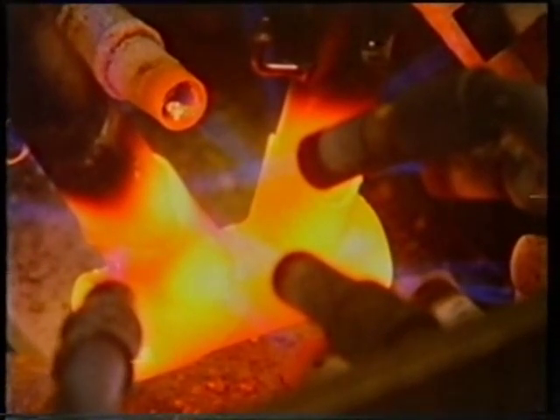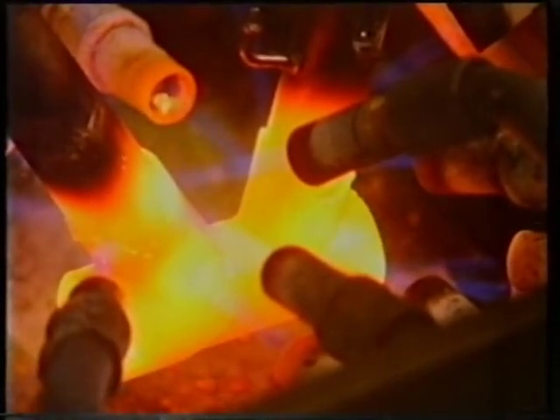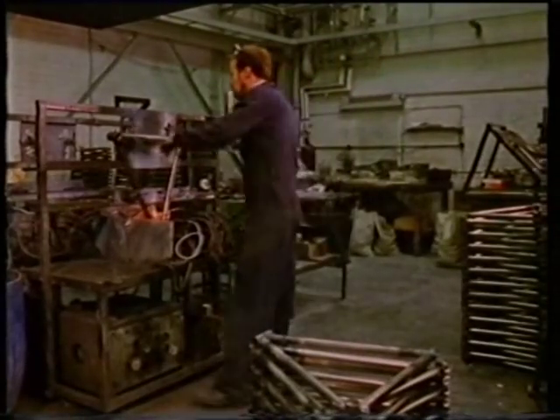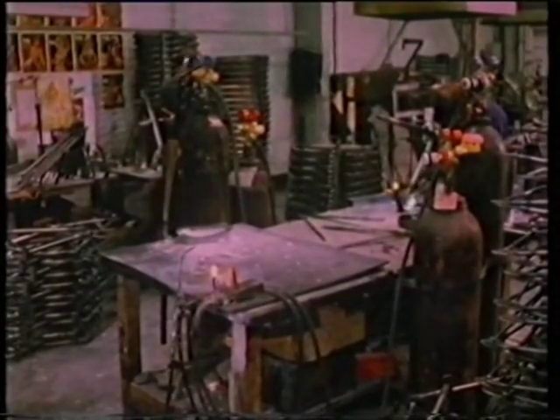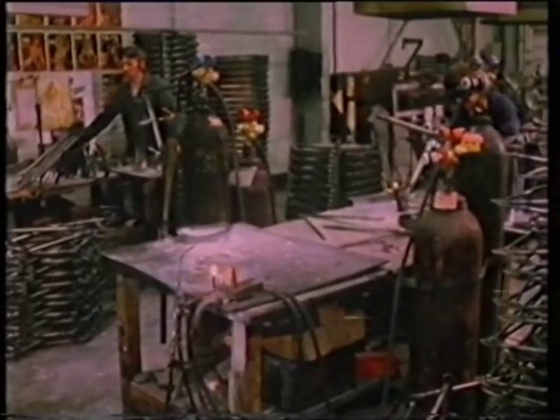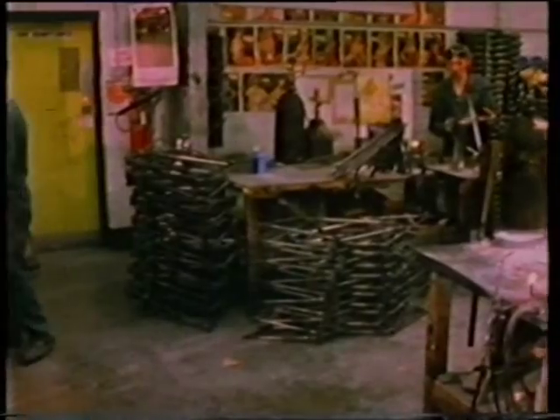The amount of brass in the insert is critical. Too little and the joint is a poor one. Too much leads to costly finishing and cleaning on the frame. To speed handling, the joint is quenched after rough cleaning. The next operation is by hand. The rear bracket of the frame is brazed on. Frame assembly is completed by a further timed process on the bottom bracket.